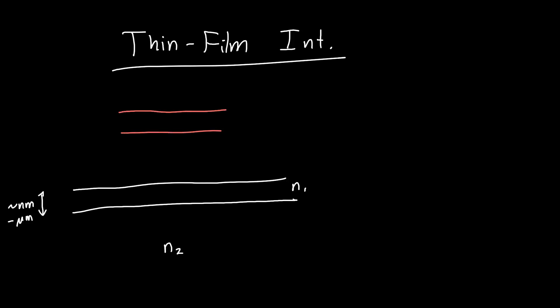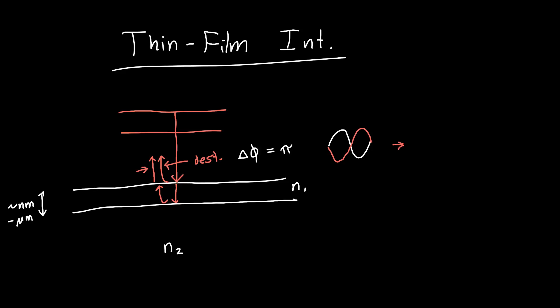When we send a plane wave — or equivalently a ray — at this film, we know that some of that ray will bounce straight off, but some will get transmitted into the film, bounce off the back, and then come back to join the original reflected ray. If we can get these two rays to destructively interfere, we can get less reflection from this interface than we would otherwise. We do this by having a phase difference of pi between the waves — that is, one has traveled an extra half wavelength compared to the other — so together they cancel out and give you nothing.